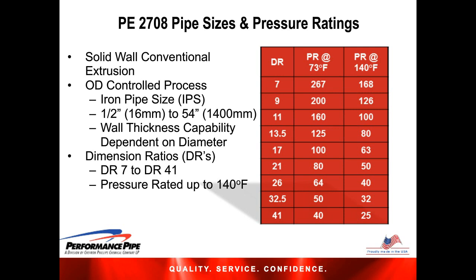PE 2708 pipe and fittings are pressure rated up to 140 degrees Fahrenheit, with the DR11 having a pressure rating of 160 psi at 73 degrees Fahrenheit and 100 psi at 140 degrees Fahrenheit.